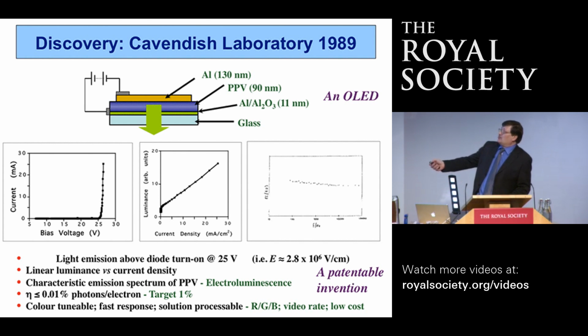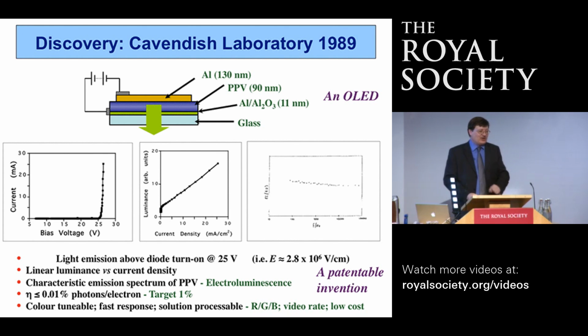And so a very simple structure was made, essentially aluminium on both sides. One side has a thin layer of oxide because it was exposed to air in the preparation of the device structure. And the idea was simply to crank up the voltage and see when this thing failed. And that would be your dielectric breakdown strength. Now, there are obviously much more scientific ways of working that out. If you do dielectric spectroscopy and all sorts of other things, this is the quickest way to find your answer. So that was actually the experiment that was done.